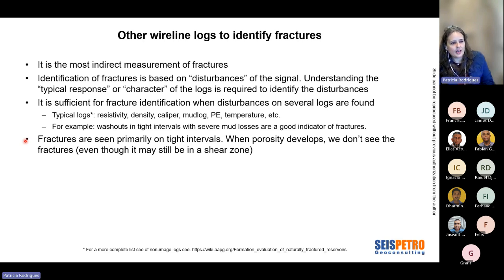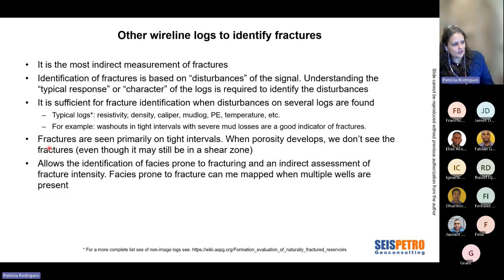But when porosity develops, we don't see the fractures. Even though maybe they are still in a shear zone, you don't see the fractures because the deformation can be accommodated by the grains and the pores. Sometimes they're there and you just don't see them in the measurements. Looking at other wireline logs will allow you to identify facies that are prone to fracturing. And it can be, again, an indirect assessment of fracture intensity. That's more like a stretch. It would be only on few occasions that we can see that.